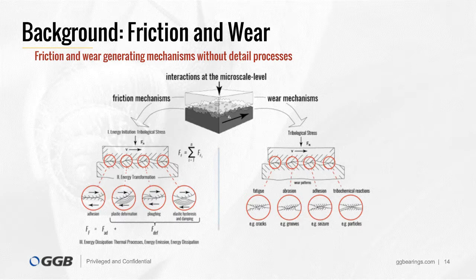The wear mechanisms on the right side are adhesion, abrasion, fatigue, and tribochemical reactions. The typical wear patterns are shown in the images below. Cracks are typical wear patterns for fatigue, often a result of repeated stressing of the surface.